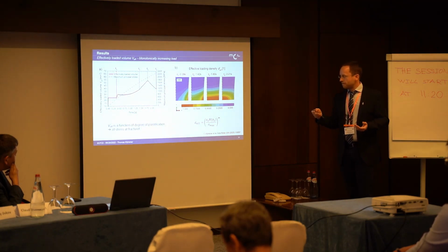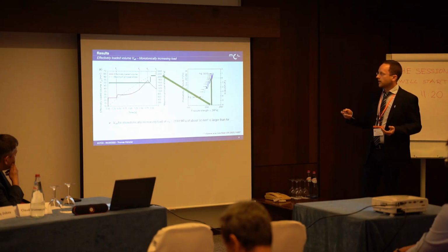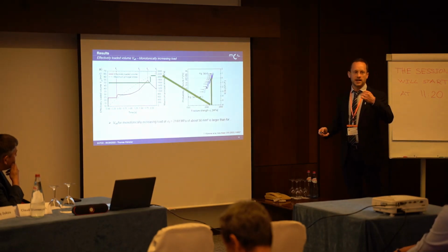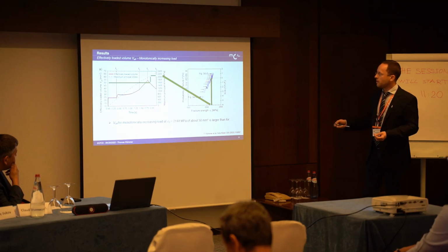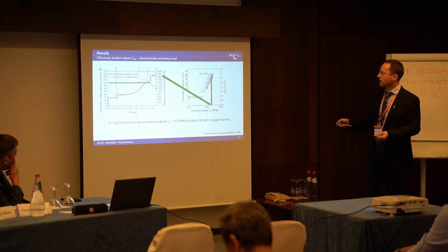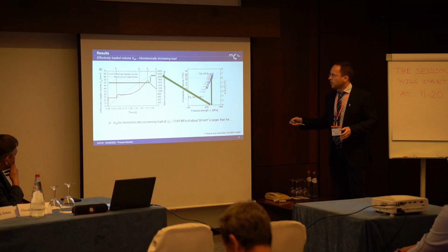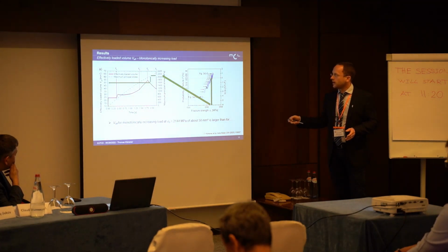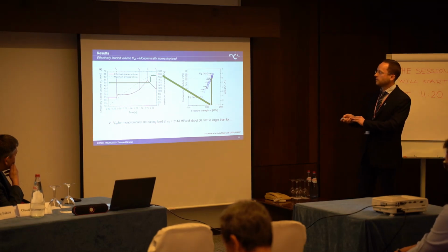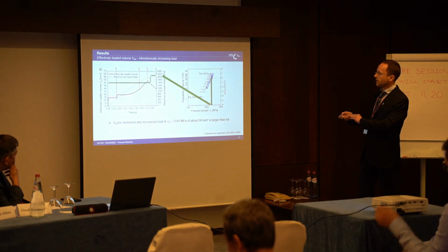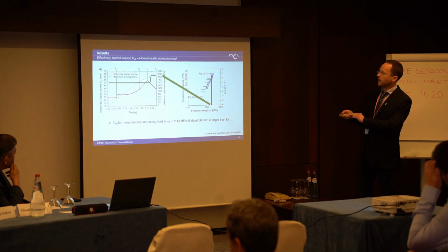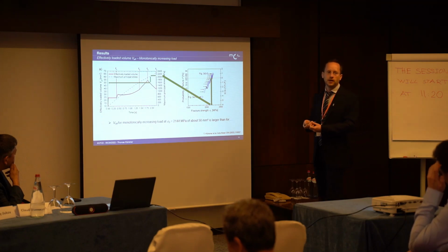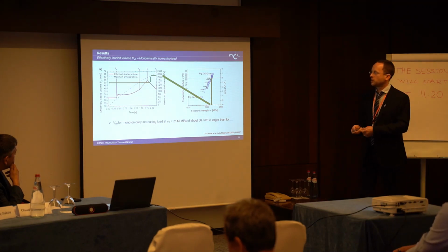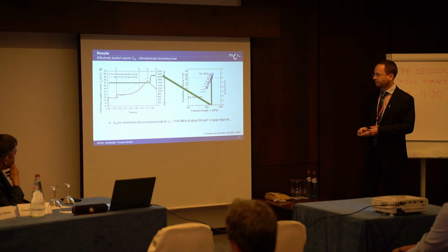And if you consider that the effectively loaded volume is a function of stress at fracture, then, if you remember those results here, sigma 0 was about 2,100 something. If you go on here, you can read here this blue is the maximum principal stress, and you have to correlate it with this point here. That's why I drew all those arrows to make it more readable, so to say. Stress at fracture, go here, and then you find out it's about 50 cubic millimeters. That's lower than the room temperature with no plastification before fracture.